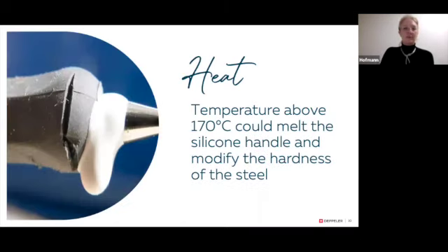Finally, the heat. As I said before, the heat will change the quality of the steel, but you will not see that unless you have instruments with a silicone grip or a plastic grip that supports a little bit less of the heat than steel itself. But for example, here it melted and the temperature was over 170 because this is the temperature where the handle begins to melt. And actually controlling the quality of the steel, we find out that it changed the hardness. So if you have instruments where the handle begins to change, it might be because of the temperature of the sterilizer. Usually it shouldn't happen, as the regulation is that it shouldn't be more than 134 degrees.